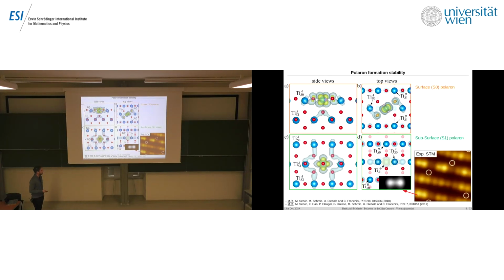For the moment, I want to mention that this polaron is also predicted to be more stable than a polaron on the surface by density functional theory calculations, if you carefully consider the parameters that you use for the exchange-correlation correction and also for your lattice structure.